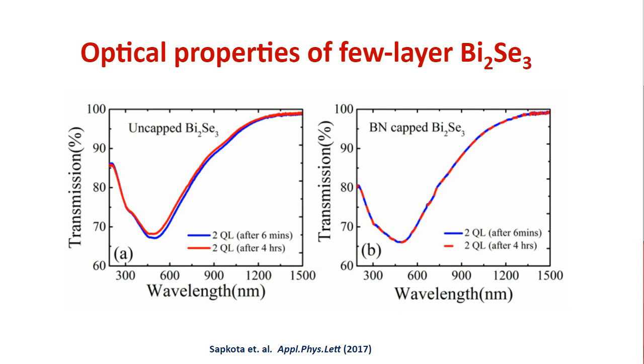They overlap on top of each other practically. One was taken 6 minutes after deposition and the other 4 hours after deposition. 6 minutes is the time we needed to bring the sample from the deposition chamber to the optical spectrometer. And in the case of the uncapped sample, we saw that there is a small change.